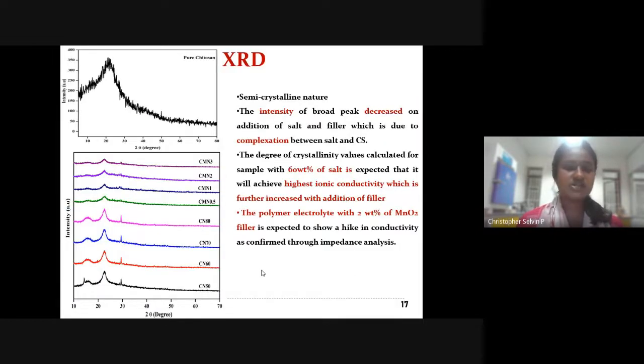So these are the XRD patterns of the prepared electrolytes. The first one shows the XRD of the pure chitosan, from which we can confirm the semi-crystalline nature of the pure chitosan. And this broad peak has decreased on adding the salt and the filler, which confirms the complexation that has taken place between the salt and the chitosan polymer. The degree of crystallinity values calculated show that the sample with 6wt% of salt is expected to achieve higher ionic conductivity, which is further increased with the addition of filler.